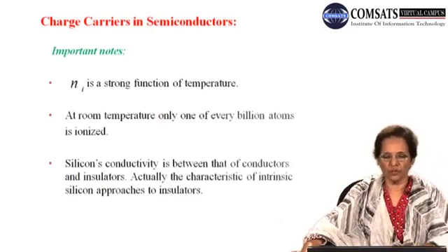Again, a repetition of what I said: the intrinsic carrier concentration, that is the carriers which are generated thermally in pure material, is highly temperature dependent, and very few bonds are broken, as I explained in the previous 2 or 3 slides. If there are 10 to the power 22 atoms per unit volume, then at room temperature only 10 to the power 10 bonds are broken. So this is not a very large number.